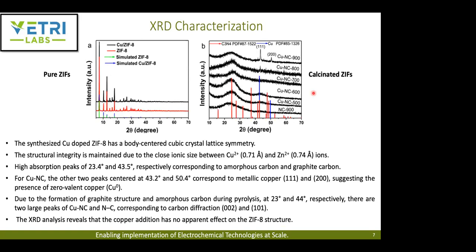To confirm the presence of copper doping in the ZIF-8, they did XRD characterization. As you can see, the synthesized copper-doped ZIF-8 has a BCC crystal lattice symmetry, and the structural integrity between the ZIF-8 and the copper ZIF-8 is maintained. It's not changed much because the copper ionic size and the zinc ionic size are almost the same. With these calcined ZIFs, you can see high absorption peaks at 23.4 degrees and 43.5 degrees, corresponding to amorphous and graphitic carbon.